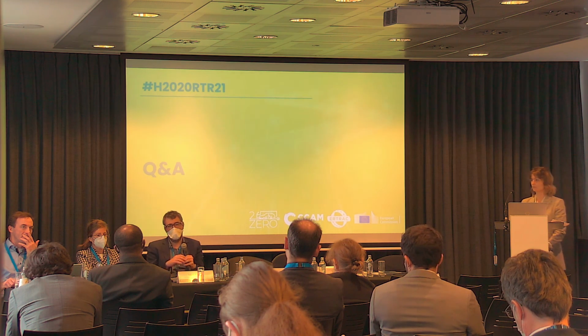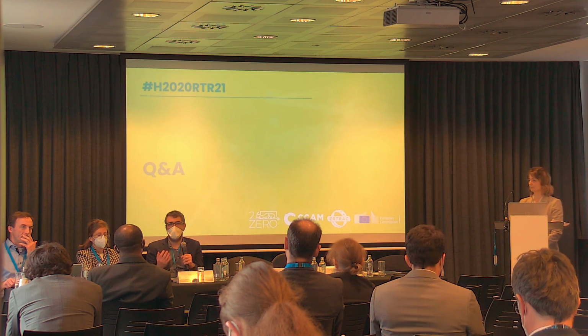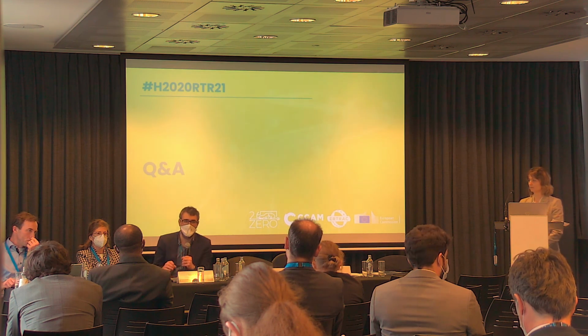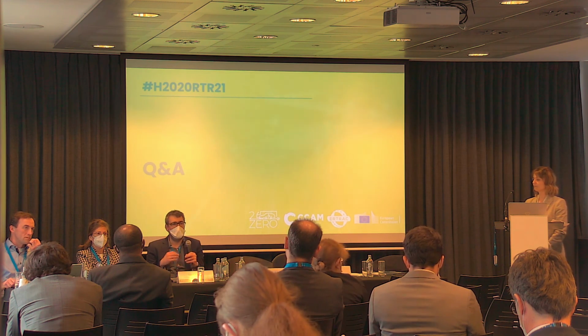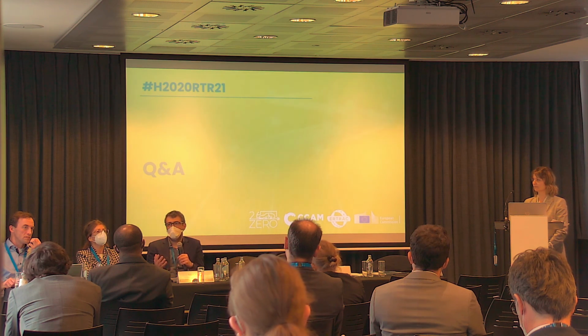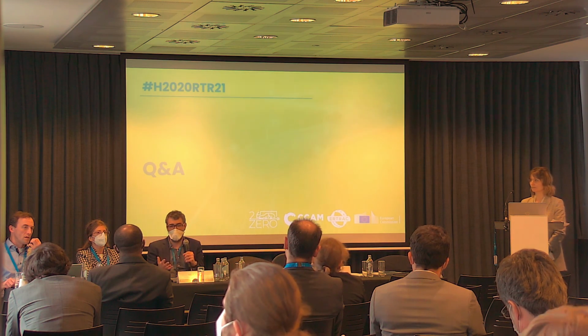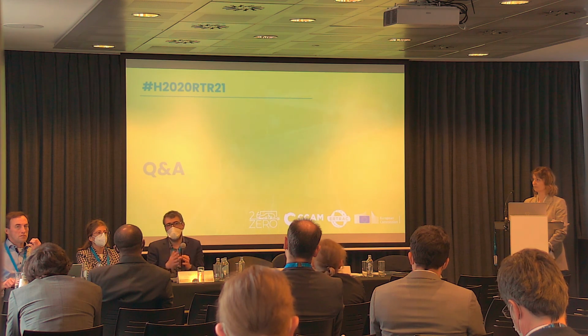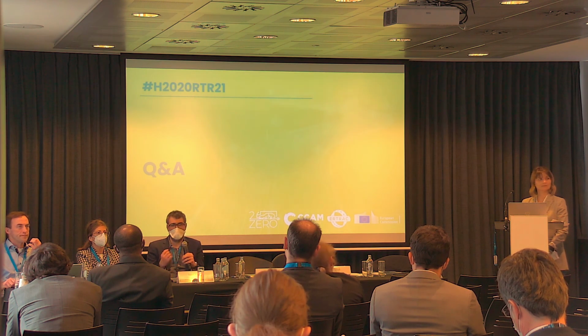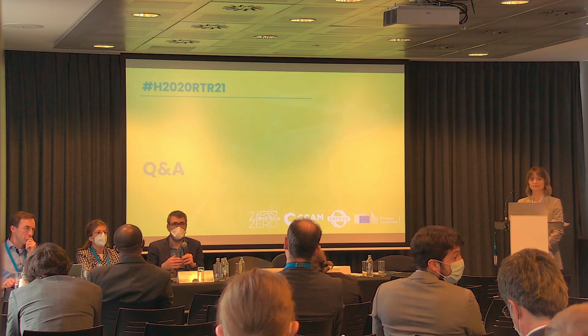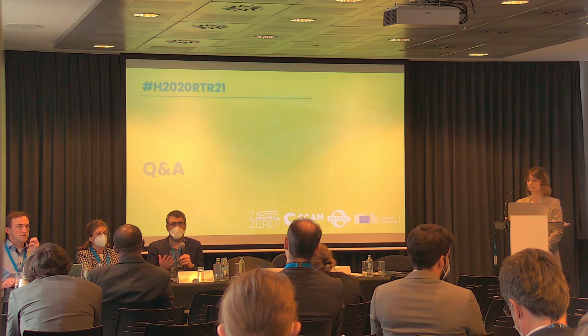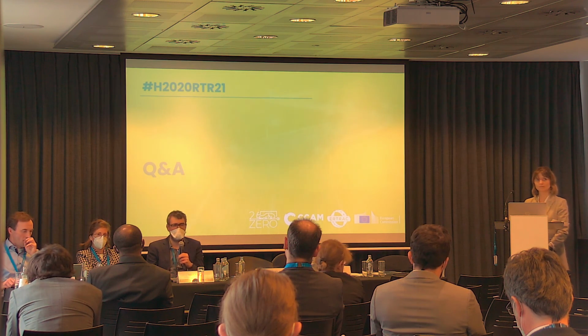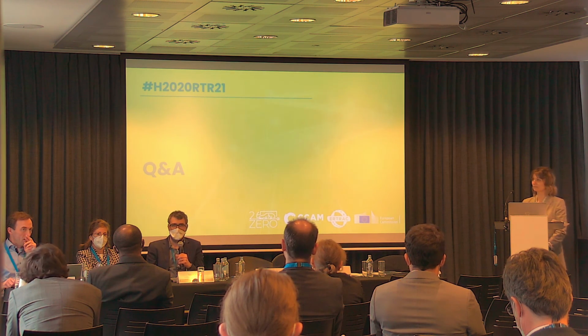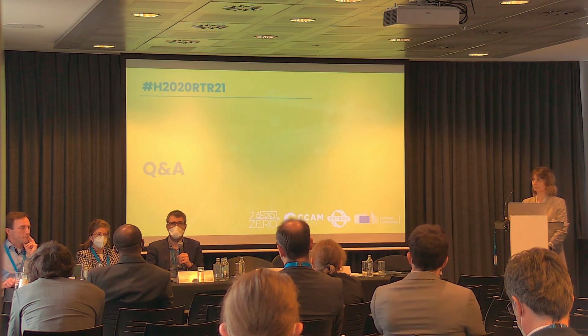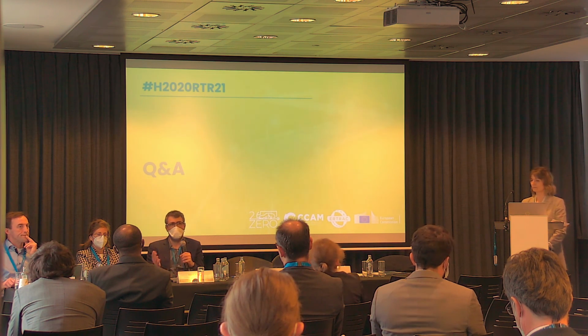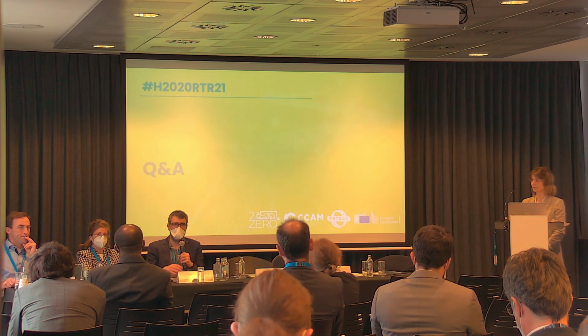And what we want to do is to have the most generic approach possible in order to account for variability in the processing, variability in the materials, and variability in the mixing and formulation of electrodes. So for instance for DEM, we will have some kind of springs that will model the mechanical behavior of the cell, and we want to evaluate the stiffness, and this will not be impacted by the amount of silicon or graphite, and we can adjust this to see the implication of this amount of silicon. So for the moment, we focused on the formation that we have in real life to compare it with the model, and then we will extrapolate to see the implication of higher silicon content and so on.